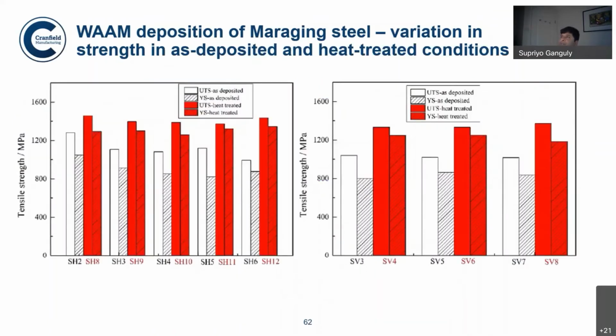Now the left hand side shows the horizontal tensile strength results, and the right hand side the vertical ones. As you can see, the heat treated ones have gone up quite significantly in strength compared to the as deposited ones, which is quite expected. However, it never achieves 100% of the wrought alloy strength. If the strength is about 1700, it is coming to about 1500 or so.